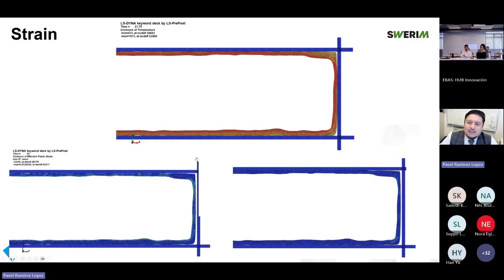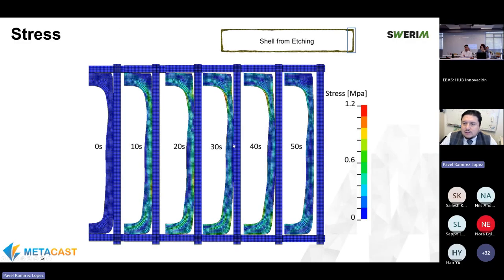So this is in terms of strain, and it helps us to understand better, for example, when we have good contact or not, and the formation or accumulation of stress as a function of specific shells that we obtain either from etching, with the help of our students, for example, who have done superb work on etching samples from big slabs, and they have translated these shells into FEM. Or from our digital twin calculations in Fluent, for example, we are able to extract these shells and put them under this reverse modeling approach.